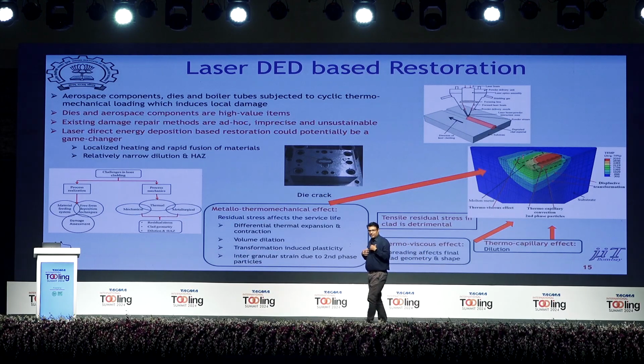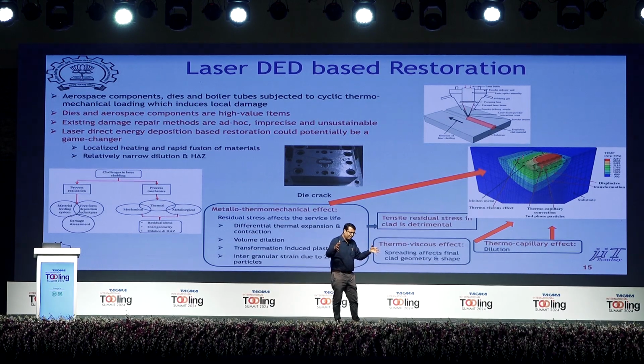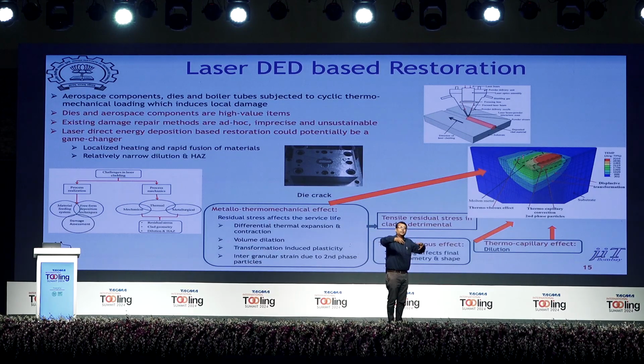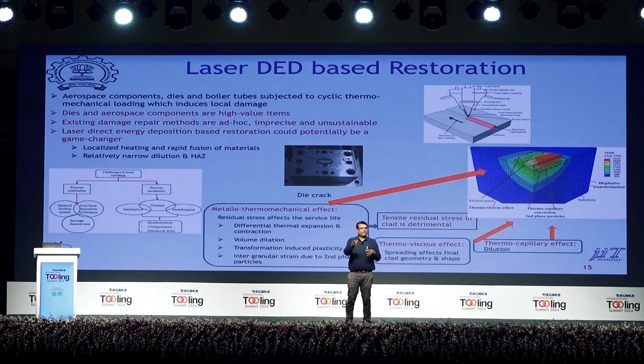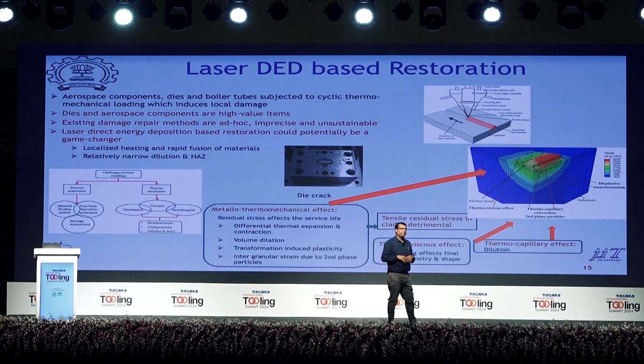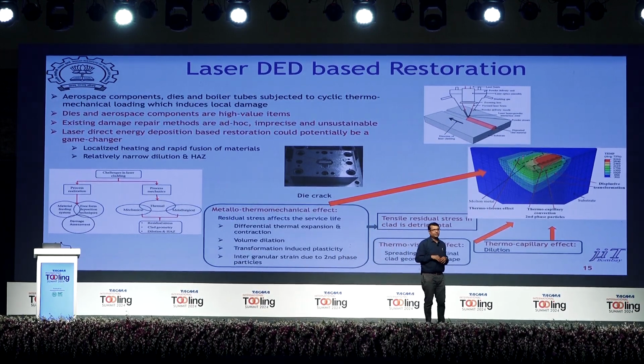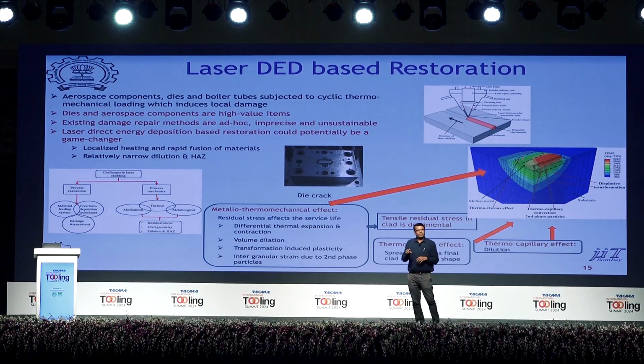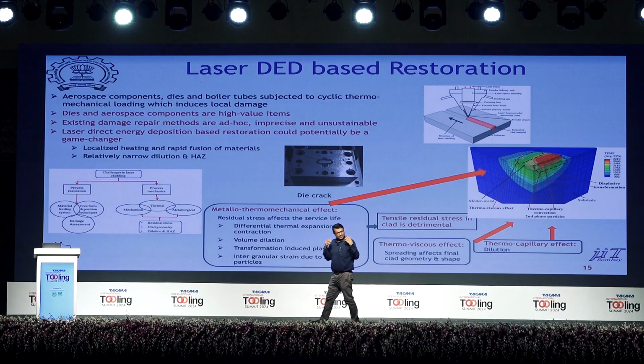So one of the things I want to understand is when I'm depositing, especially steels, right? I'm depositing steel on a mold. What will happen is there will be differential thermal contractions. There will be residual stresses because you're depositing hot molten material on top of a cold bulk of the steel. So there will be differential thermal contraction and that will create stresses. Not only that, because the rate of cooling is very high, there will be metallurgical transformations. And the combined effect would basically decide what will be the life of your die. So you need to understand the science.